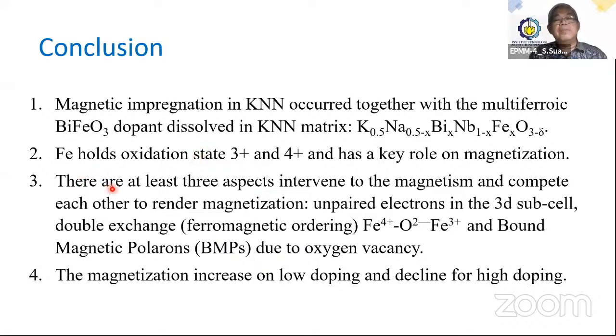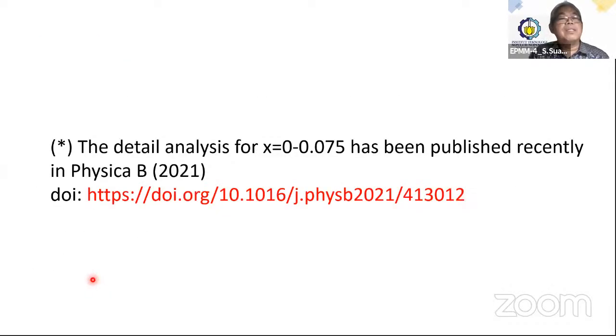There are at least three aspects that intervene in the magnetization and compete with each other to render magnetizations: unpaired electrons in 3d subcells, double exchange of ferromagnetic ordering, iron 4 to iron 3, and bound magnetic polarons due to oxygen vacancy. And finally, the magnetization increases at low doping and declines for high doping.